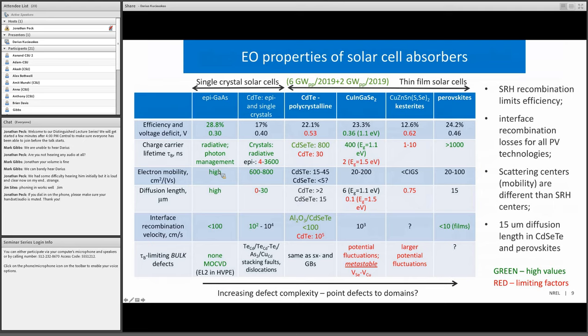And the comparison is made between the single crystal solar cells, gallium arsenide, and single crystal cadmium telluride, as well as polycrystalline cadmium telluride, CIGS, kesterites, and perovskites. In this table, I include charge carrier lifetimes, electron mobilities, diffusion length, interface recombination velocities, and in some cases, identification of specific bulk defects. So the lifetimes are great in single crystals. They radiate, in a sense they're as high as they could be. The recombination centers in single crystals are effectively eliminated, but single crystals are expensive.